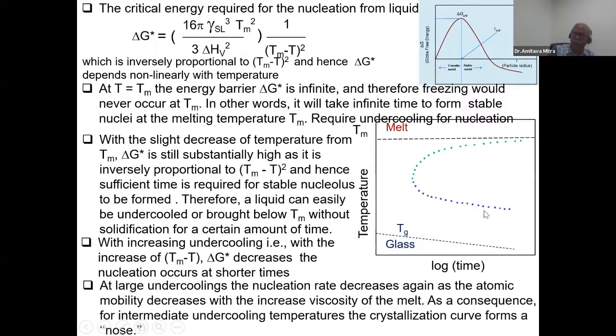This is the transformation curve, showing at which temperature and time this transformation takes place — the point where nucleation takes place, becoming the onset of crystallization for this material. So if we want to cool down now from the melting point temperature following this path, and this path curve cuts at this point, this temperature, the crystallization starts, and then the process of crystallization takes place.